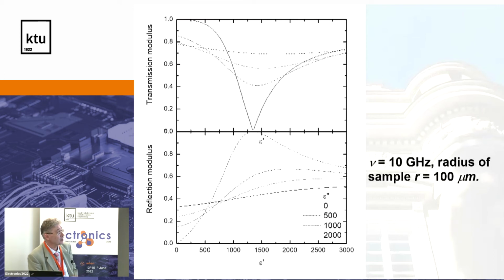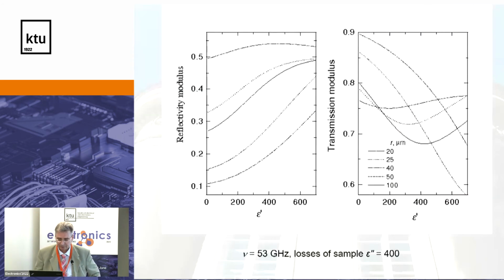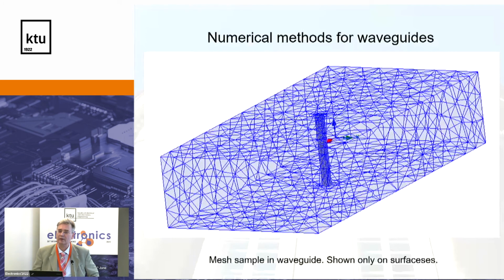And here is an example at 10 gigahertz, radius of sample 100 micrometers, and you see how reflection modulus and transmission modulus are changing, and here we have resonance, and of course better to measure before resonance. So with such a thickness you can go only up to 1,000 of the value of dielectric permittivity. So again, numerical methods to prove that our method is working, and it's working very well.